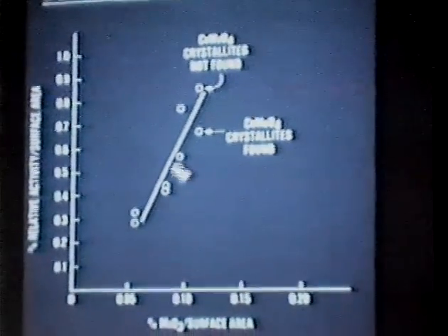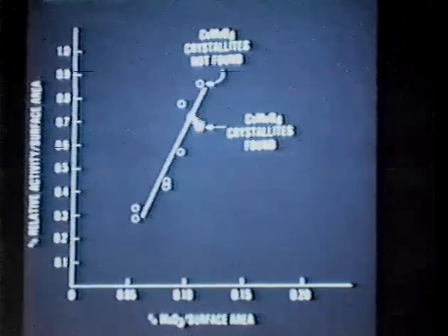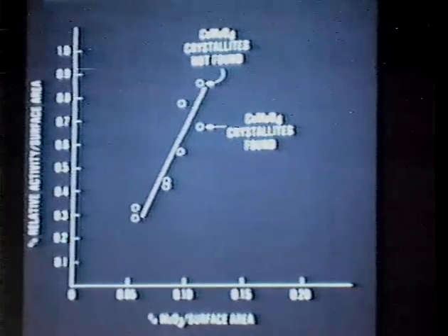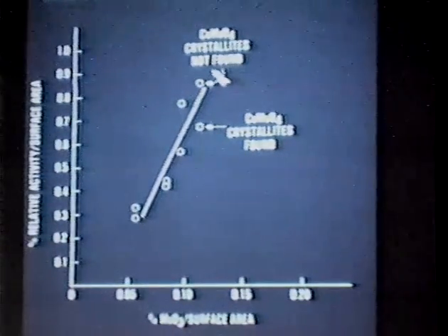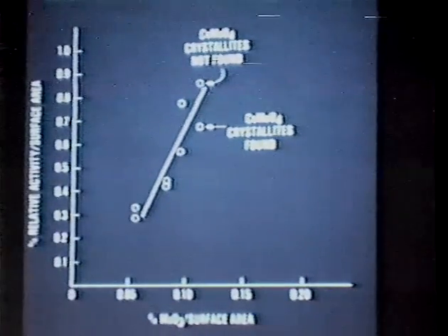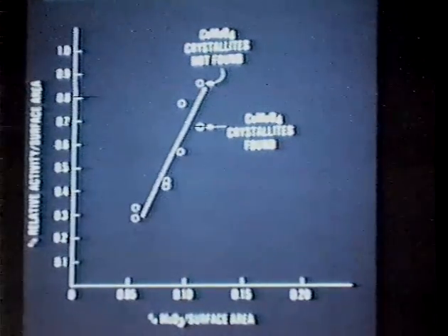I was overjoyed the first time I ever saw this plot, because it indicated that our model was maybe valid. We could at least draw a straight line through the data points we had. One interesting aspect here that we felt was important too is that we subjected all these samples to X-ray diffraction to see if we could find CoMoO4 in the finished catalyst.